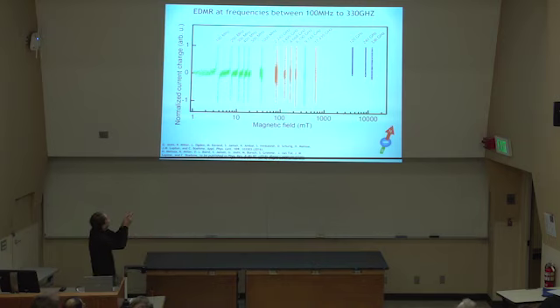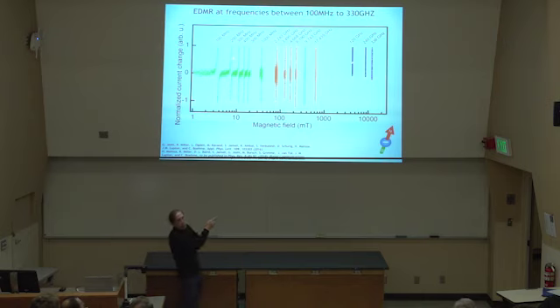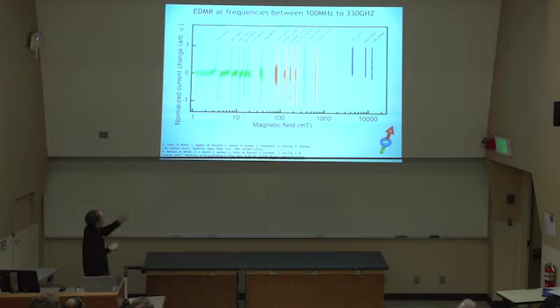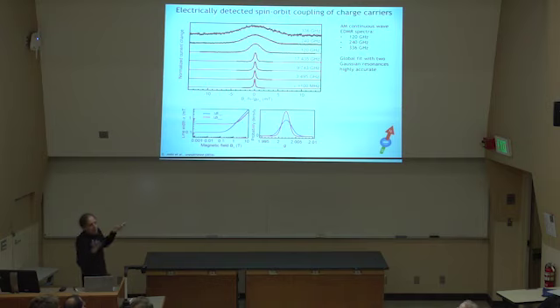That corresponds to a frequency range of roughly 100 megahertz to 330 gigahertz. And sometime soon we'll do it at 700 gigahertz, so maybe we will get to terahertz. And if you look at this plot, you finally understand why resonance lines are called resonance lines, because we have all these lines here. And now, of course, you want to expand them and do line shape analysis under all these conditions, which for this material, PEDOT:PSS, looks like this. And you see it at 100 megahertz, and then you jump here.